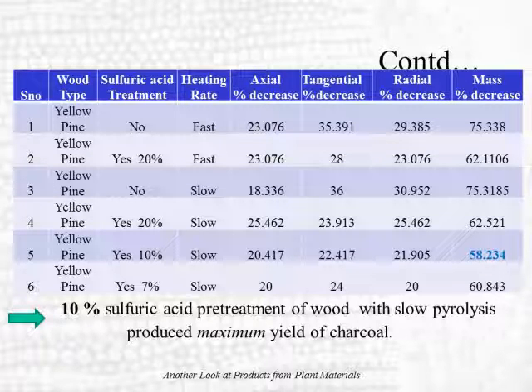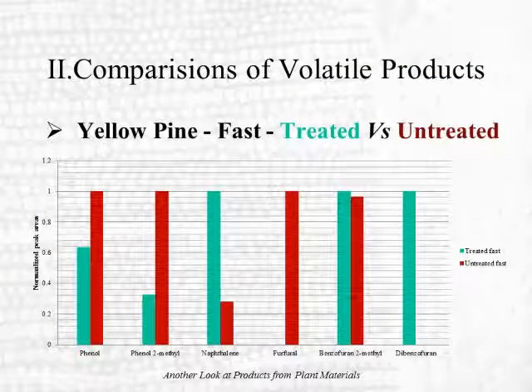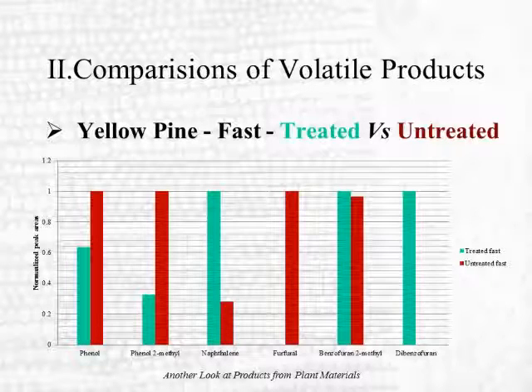increase mass yield of the charcoal. I'm misspeaking, I'm sorry. Mass yield of charcoal is typically on the order of 20 or 25%. Therefore, the mass decrease should be on the order of 80 to 75%. So in this right-hand column, what we found is that the greatest carbon yield, or the least mass decrease from carbonization, occurred with a sulfuric acid pretreatment of 10%, which means essentially that less goes up the smokestack. So we have a maximum charcoal yield when we do a sulfuric acid pretreatment.